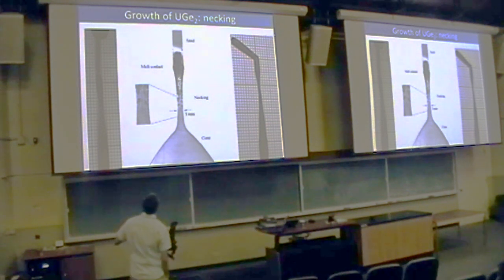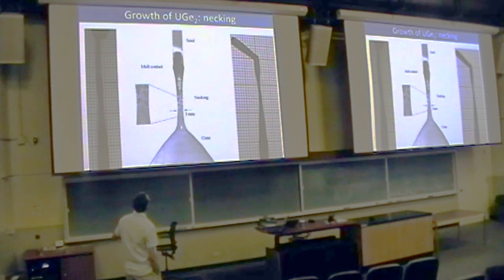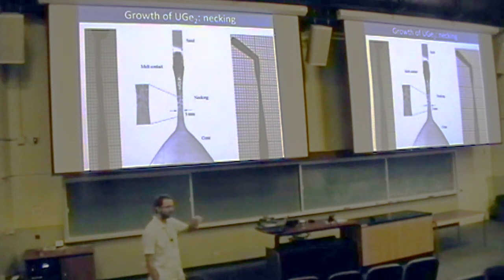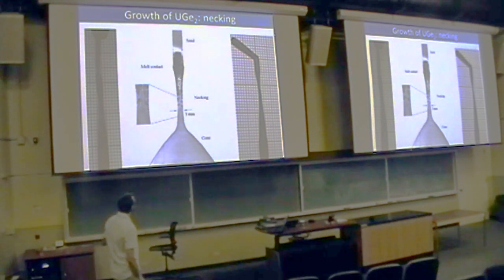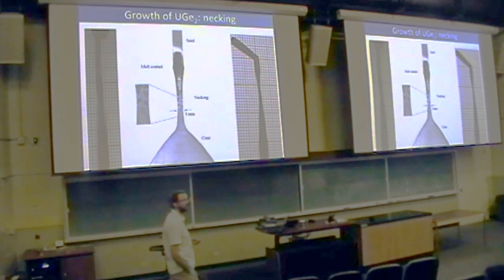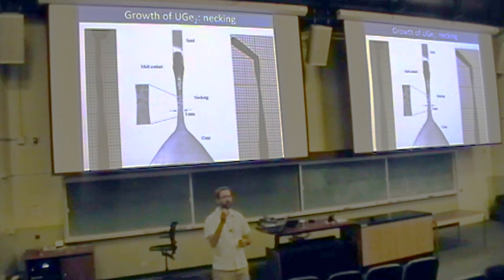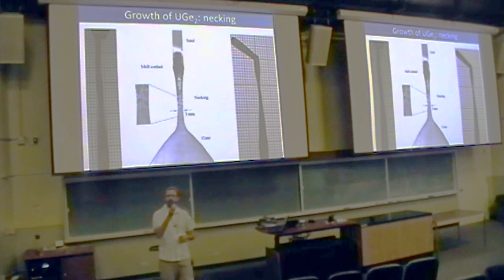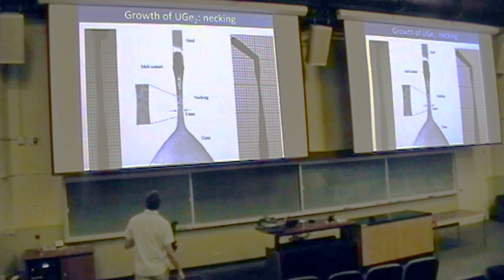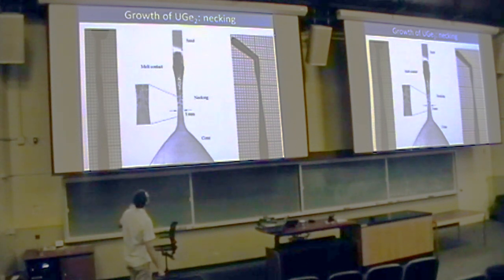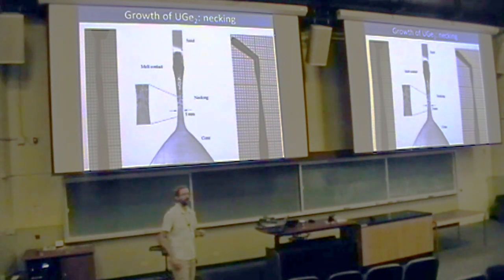So you're going to pull the crystal for a certain time by keeping the diameter of your crystal rather small, or even you can try to reduce it. And the hope during this process is that you have many grains that formed during the quick crystallization, and one of them is going to grow larger than the other, and the others are going to disappear, or are going to become smaller and smaller. And so the hope is that we start to get just one type of single crystal in this process.